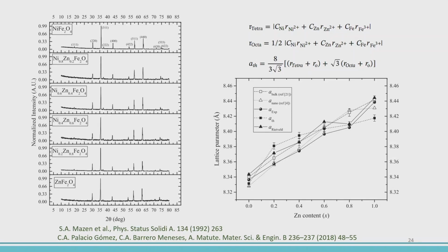But perhaps you know, from X-ray diffraction we have two different ways to determine the cationic distribution. One is from the unit cell, the lattice parameter as shown here. You see, this is the theoretical parameter where we can have the radius of the tetrahedral and the radius of the octahedral, and here we can put whatever we want, but with physical meaning. You notice here that we are not saying that nickel is only for the tetrahedral, but we assume that we can have nickel at both sites.